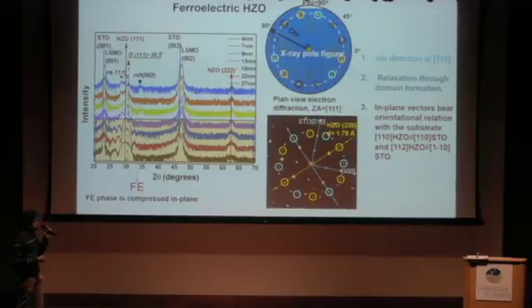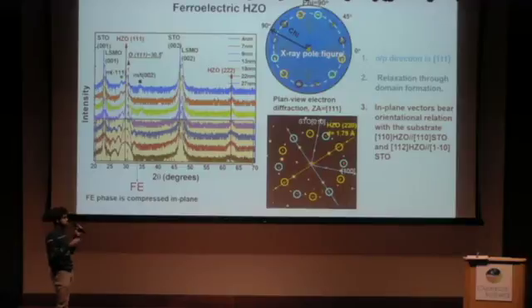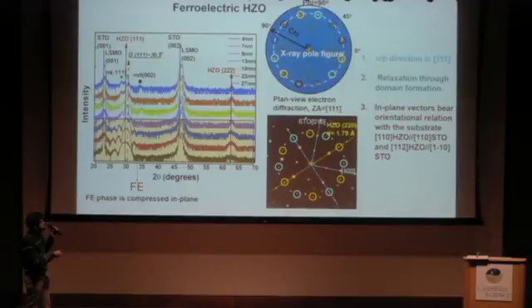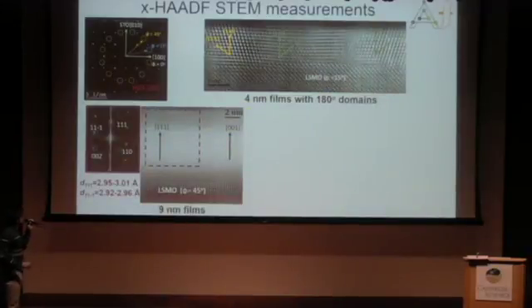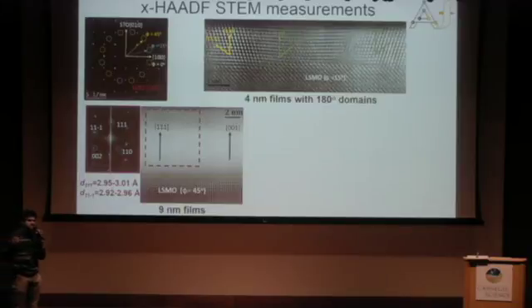Plane view TEM also says the exact same thing, TEM diffraction. So I circle spots here in yellow, coming from 2 sets of domains, and in blue coming from two other sets of domains. And also we see a clear orientational relationship between the substrate and the film. Okay, so very quickly, because I don't have much time now, we do also cross-sectional STEM measurements by making cross-sections. So this is the plan view, along several directions to get insights into what's happening.